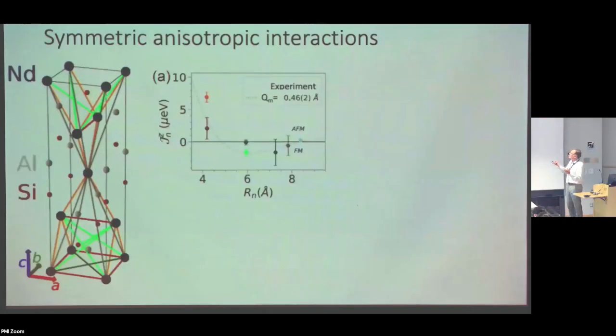And so the error bars that I'll now show, we're quite confident about those error bars. When I show this point, this is the range that we have, and for this point, that's the range. For these, we actually know them quite well, and Chris understands what happens when you vary this particular parameter as opposed to varying these parameters. And so this is our experimental result, and each of the points is the Z component of the exchange interaction for each of the interactions that are indicated on this figure. This is something that you can't look at for a minute and absorb. But the main point I want to make is that it now is possible to really read off these exchange interactions by this process.